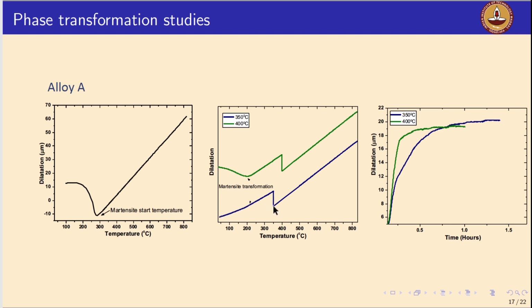So when the microstructure is cooled after bainitic holding, what you see over here is the dilatation as a function of temperature. We are cooling from austenitization, like a weld is cooled, and holding at an isothermal bainitic holding. The bainite is transforming, and upon keeping it for infinite time, when the bainite transformation saturates, if you cool back, the austenite should not transform to martensite. Unfortunately, for alloy A, you see here 350 and 400. In both the cases, when we hold at these temperatures, subsequent cooling led to martensite formation.